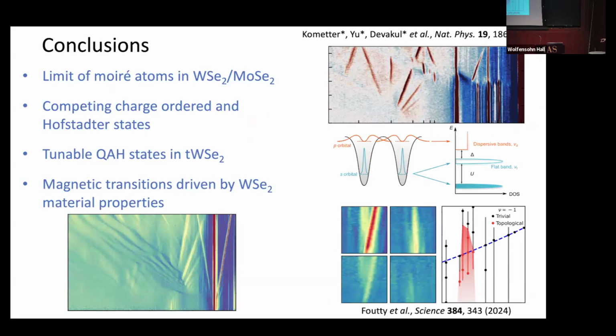And so let me just conclude. I guess what I've tried to tell you is that in these transition metal dichalcogenide systems, you realize something that is more like an effective Hubbard model than in the graphene systems. So you can look at this kind of very large twist angle limit where you have Moiré sites which are very far separated, and actually it's instructive to think about them as individual Moiré atoms. And by changing magnetic field, by changing carrier density, you can tune which of these different Moiré bands are occupied. And so you can induce magnetic transitions in that way. In other material systems like tungsten diselenide, you can tune not only the nature of which bands are occupied, but actually the topology of the underlying ground states.